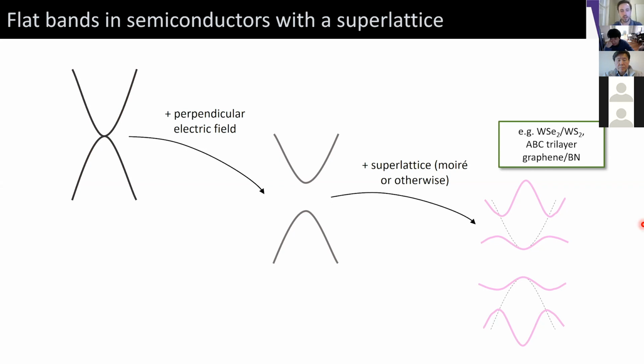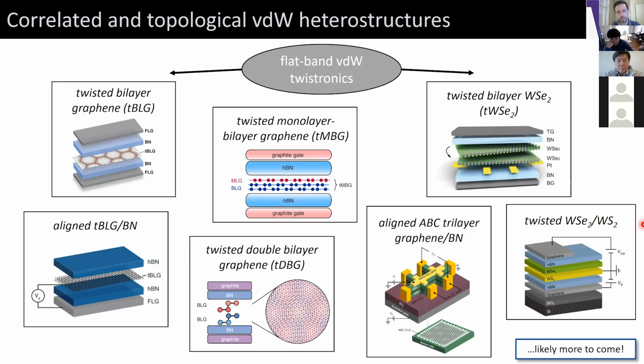So I can create this new kind of taxonomy of flat band van der Waals twistronic systems, which have correlated or topological ground states at low temperature. And to my knowledge, there are what I would consider 7 distinct systems now that have been discovered in just the past 2 years that can do this. On the left here, we have our graphene variants: twisted bilayer graphene, double bilayer graphene, bilayer-monolayer. If we align these things to boron nitride, they really form fundamentally distinct electronic states, so I'm going to consider this as a different system entirely. We can have trilayer graphene aligned with BN and even variants of twisting different transition metal dichalcogenides. And I have no doubt that there will likely be more than just these 7 discovered in the coming months and years.